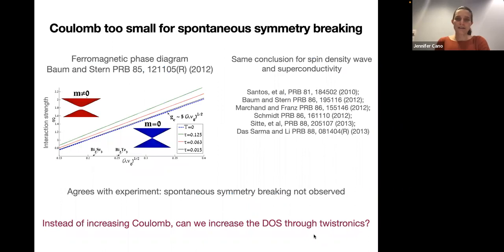So this question is not, I'm not the first person to ask this question. So I think starting from around the discovery of topological insulators, which was around, say, 2010, people have been trying to search for these symmetry broken phases. And so I'm just showing one plot from this paper, where they're looking for ferromagnetism on the surface of the topological insulator. And so what they're plotting here, the x-axis is a function of the velocity of the Dirac cone, and the y-axis is the strength of the Coulomb interaction. And so what's being shown is that we have the surface Dirac cone for small Coulomb interaction. And if you cranked up the Coulomb interaction, you would cross a critical interaction strength where you would gap out the Dirac cone, and this would lead to surface magnetism on the TI.